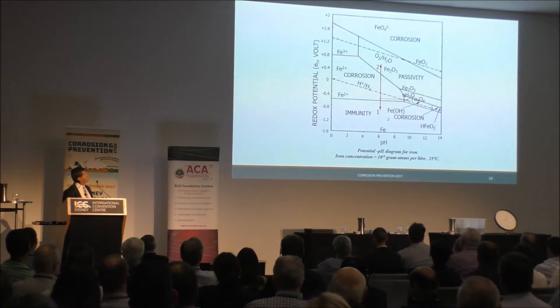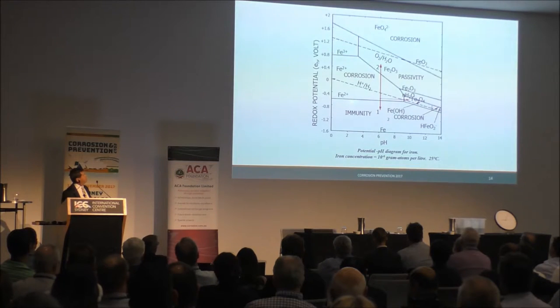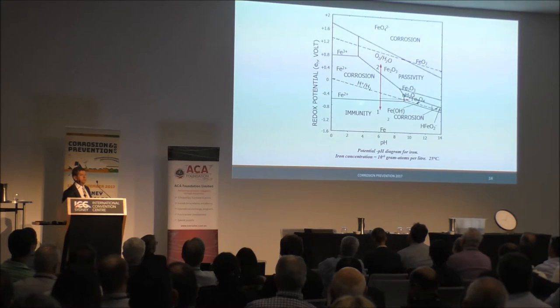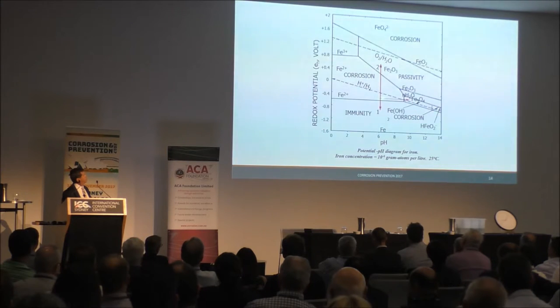So how can we use this information? Well, let's take a simple example for you. If we take a piece of iron, or steel, let's call it iron, and put it in deoxygenated solution of water where there's no oxygen present, then we would find, let's say, for example at pH 6, that the measurable electro-potential for that piece of iron in that deaerated solution would fall somewhere around here. It would fall somewhere between the equilibrium potential for iron ions in solution and the hydrogen electro-potential. So right there is where that little cross is located, that red arrow.